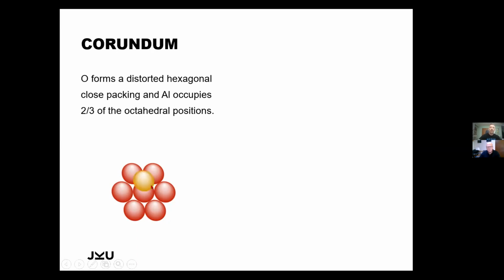So if we add a second layer on top of it, we add one ion on top of a hole, more or less. So it's in between 3 other oxygen ions of the layer that we have below. And we can go on and add up this second layer.